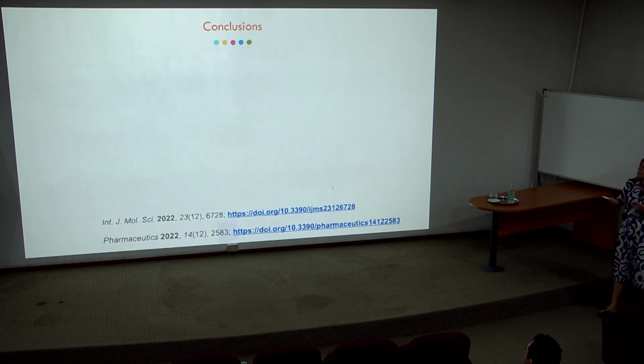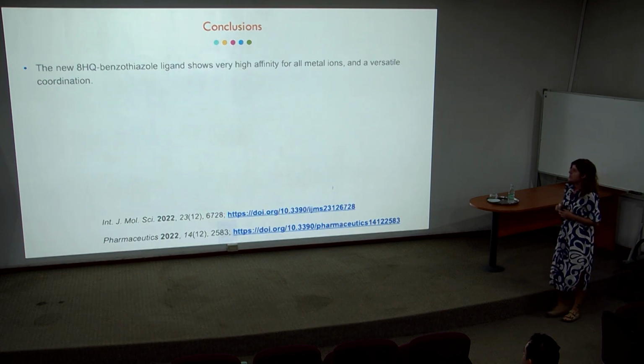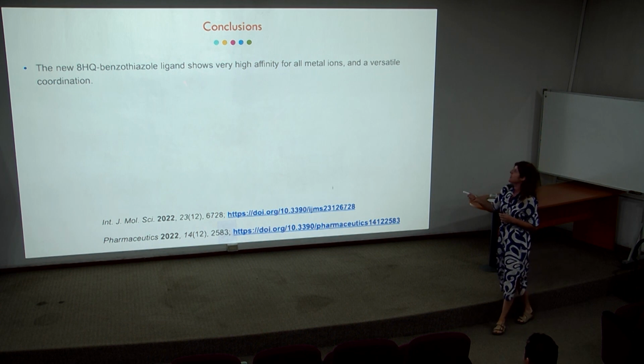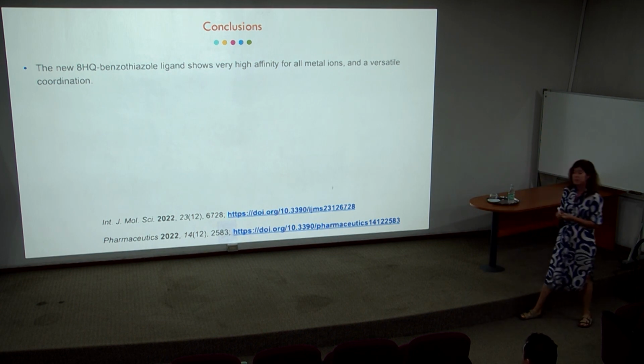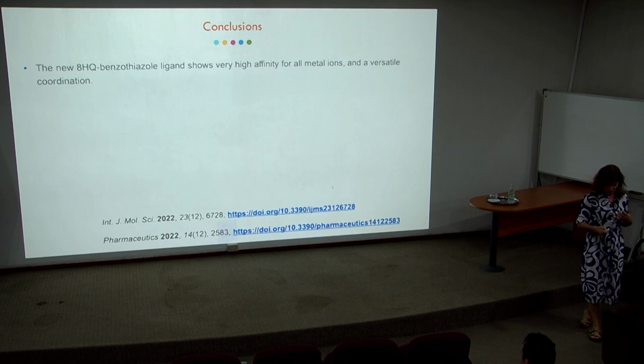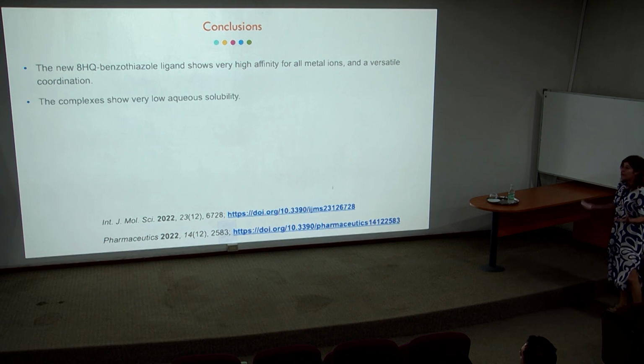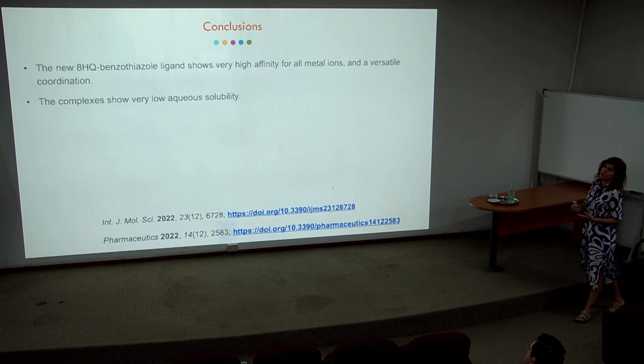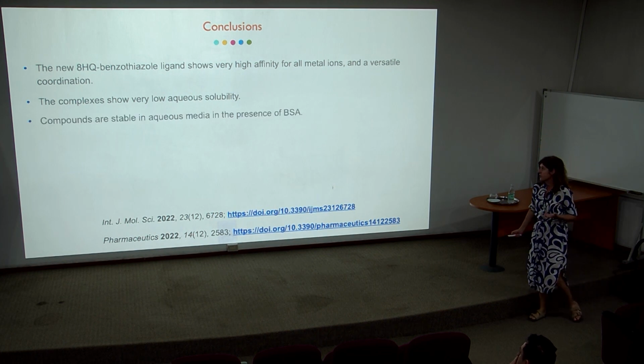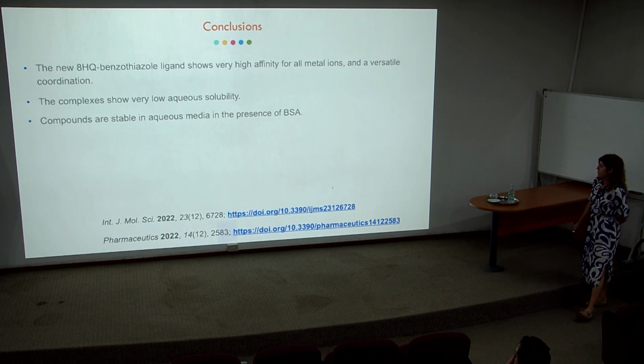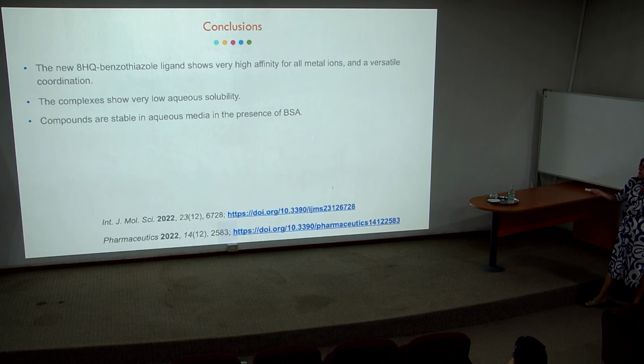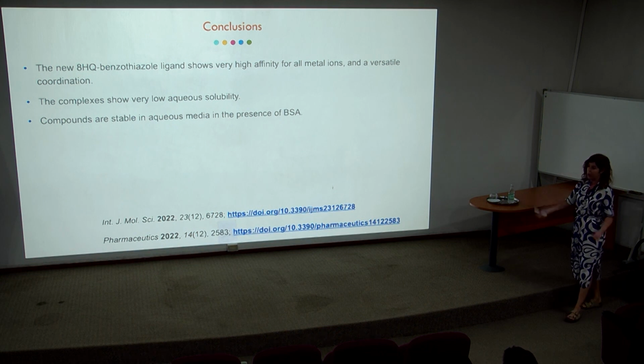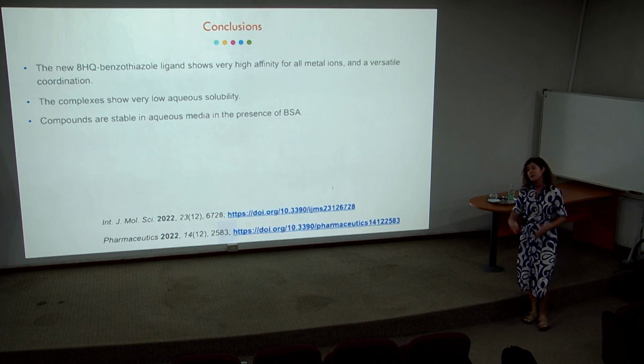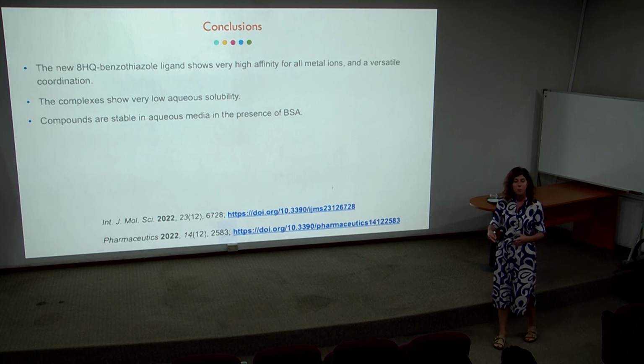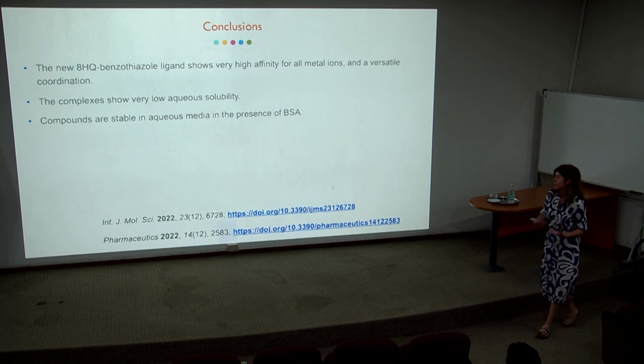In terms of what we can conclude from this study, this ligand shows high affinity for metal ions and a very versatile coordination. However, one drawback is the solubility of the complexes, which is quite low in aqueous media. The compounds are stable in the presence of albumin. This is important because we know we have albumin in the cell media, so we know that it will keep our complexes in solution. They cannot precipitate.